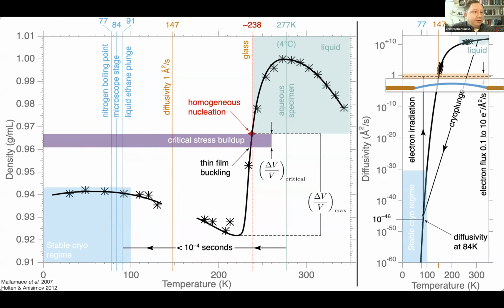And then when you put the specimen in the microscope, that pseudo diffusion of water molecules that I showed you at the beginning actually allows the water to move around on the specimen. And therefore, the strain that's caused during this cooling phase here is released because the water molecules are allowed to move again. And that's what we see as movement in the electron microscope. That's the movement that happens in the first phase. So it's an additional buckle, if you will, or bending that is releasing the strain built up during the specimen plunging process.